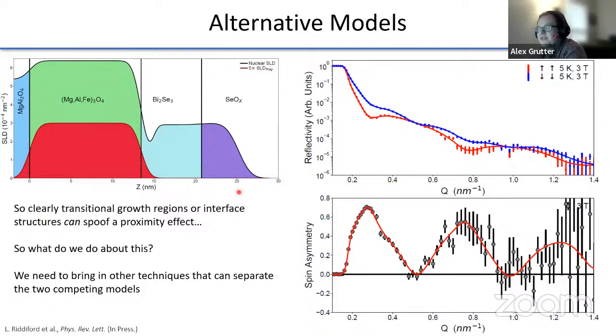Well, as soon as we do that, and we model this with no magnetic proximity effect, no sort of bump extending into the bismuth selenide, we actually catch this feature perfectly again, and we catch this feature really nicely again. And so it looks like transitional growth regions and interface structures can spoof a magnetic proximity effect.